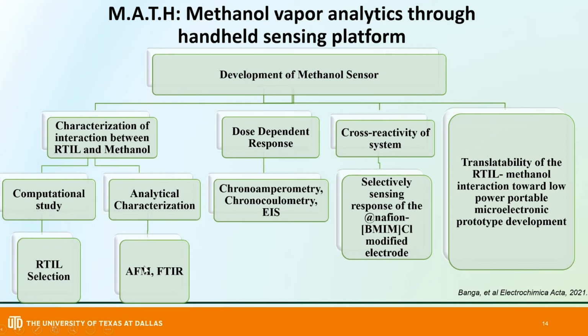The second analytical characterization was done wherein we used AFM and FTIR to see the surface characteristics. With AFM and FTIR, we were actually able to see the interaction that the computational study suggested. So we were able to do both hands-on substantiation as well as computational study to support our hypothesis. The second part was the dose dependent response that was substantiated by chronoamperometry, chronocoulometry, and EIS. All three showed specific and selective response in a dose dependent manner for methanol vapor. The cross-reactivity of the system demonstrated the selective sensing nature of the Nafion and RTIL modified electrode. And finally, all of this data was used to show the development of a low-power microelectronic platform. This data was published in an Electrochimica Acta paper.